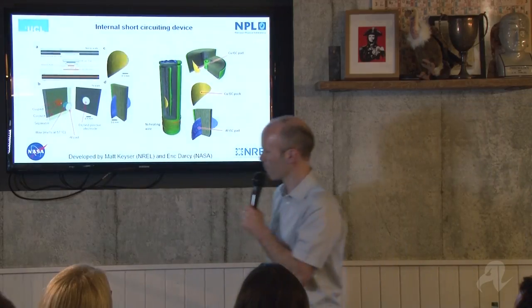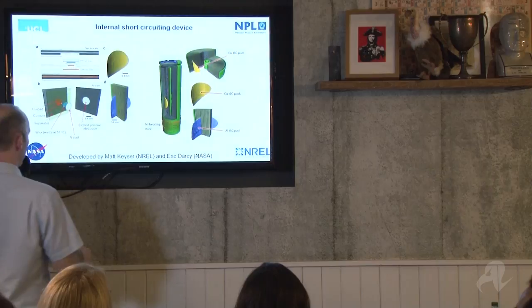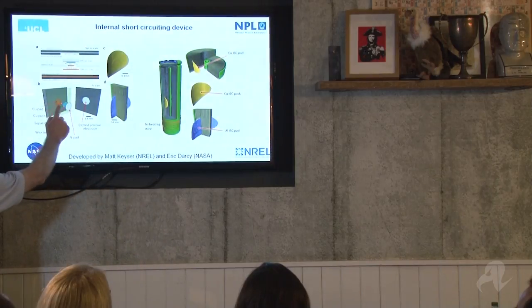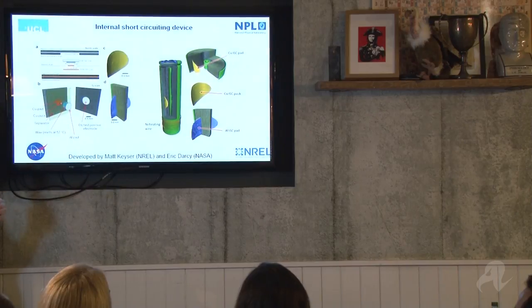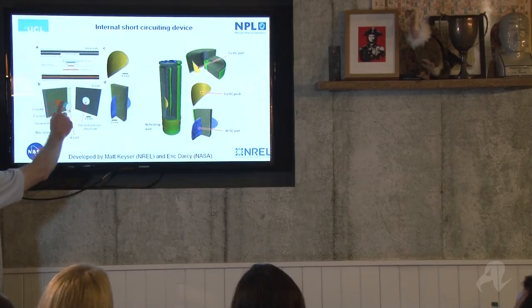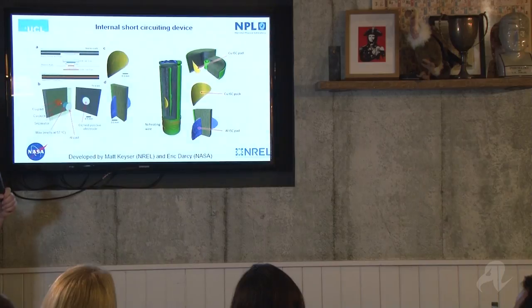So what we have is we take a small hole in the separator material, and we put a little bit of wax between a copper pad and an aluminium pad. That wax melts at 57 degrees. Then all we need to do to generate this kind of induced short circuit is to heat the battery up to 57 degrees, which is what we did. And we can put this little device anywhere we want inside one of these cells.